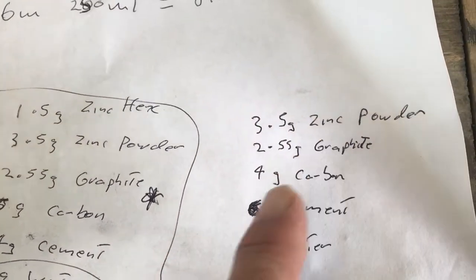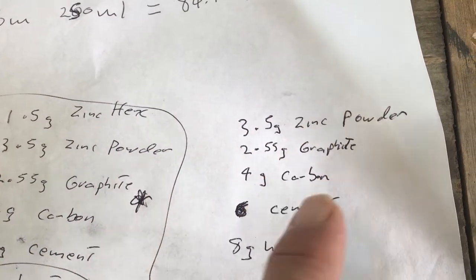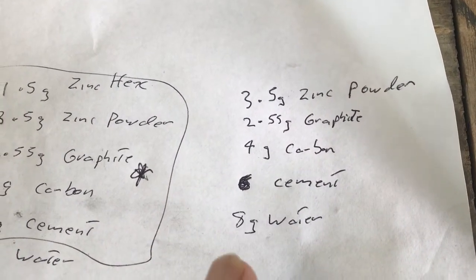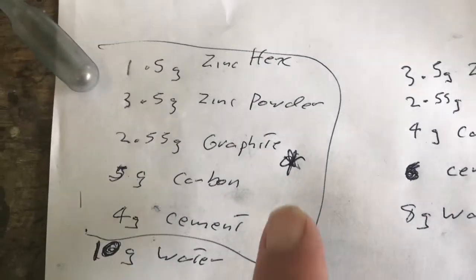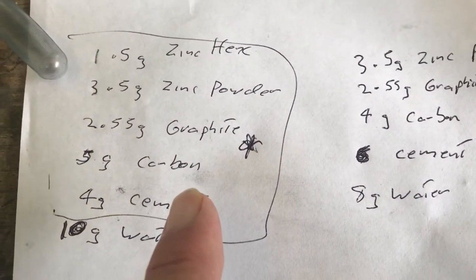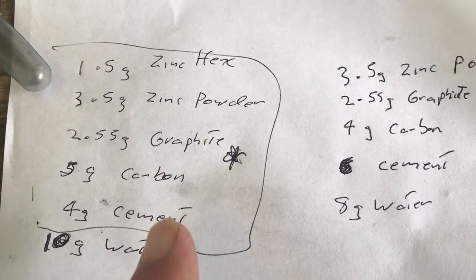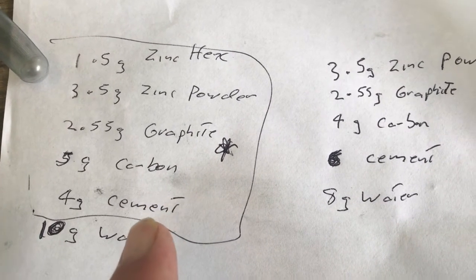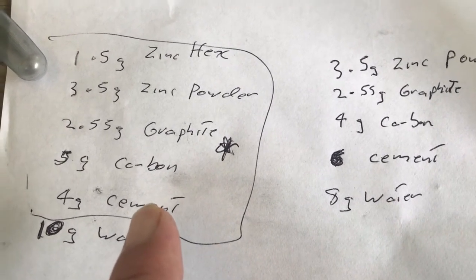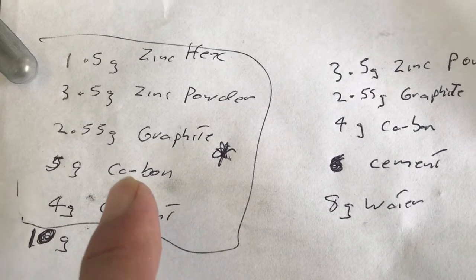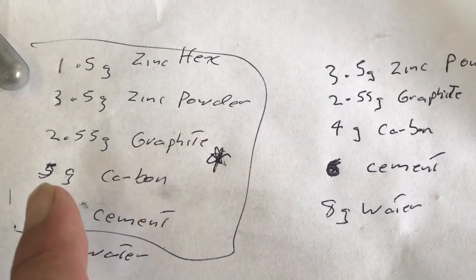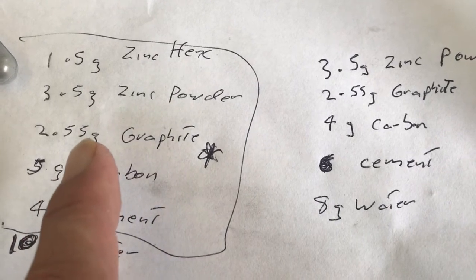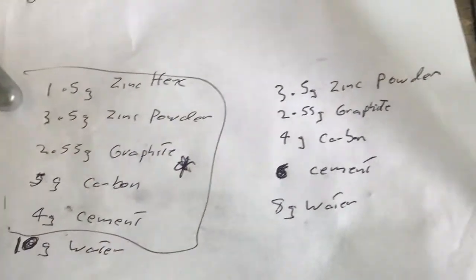Okay, I'm trying this batch today. 3.5 zinc powder, 2.5 grams of graphite, 4 grams of carbon, 6 cement, and 8 grams of water. And that's the one that failed. So slightly higher on the cement, less on the carbon by 1 gram, we use 5 there, same on the graphite and same on the zinc, and no zinc hex yet.